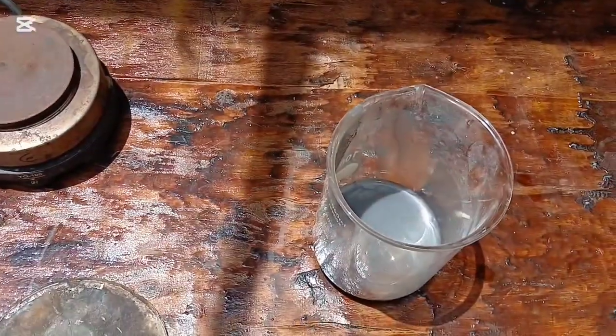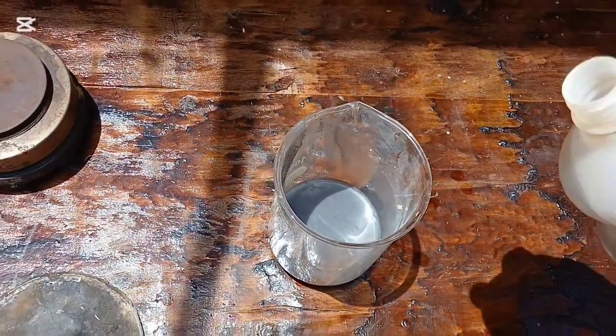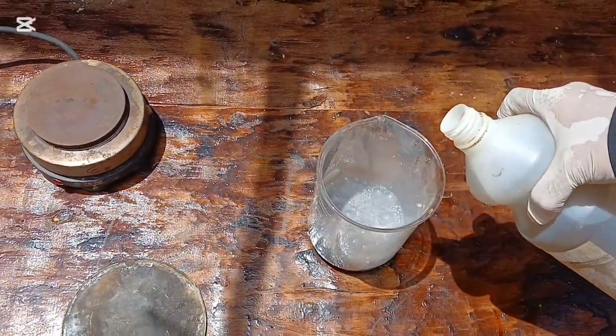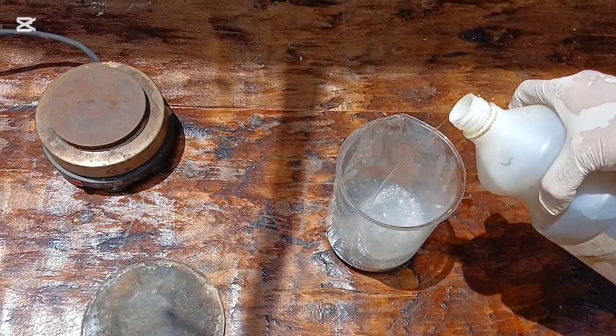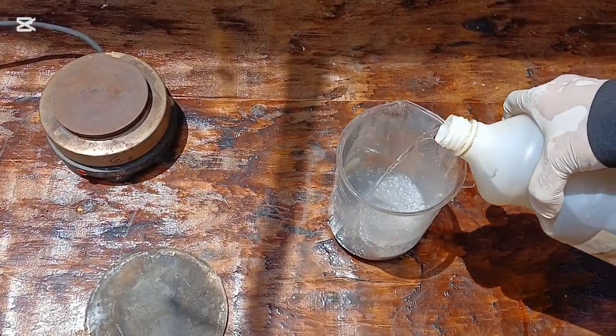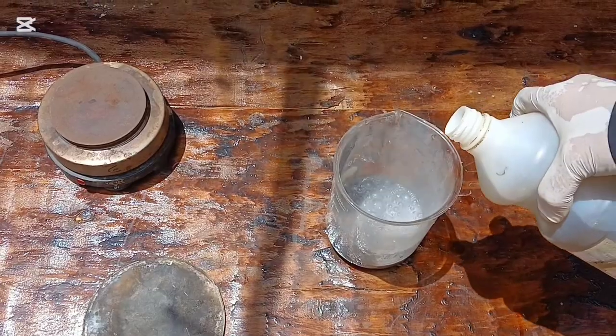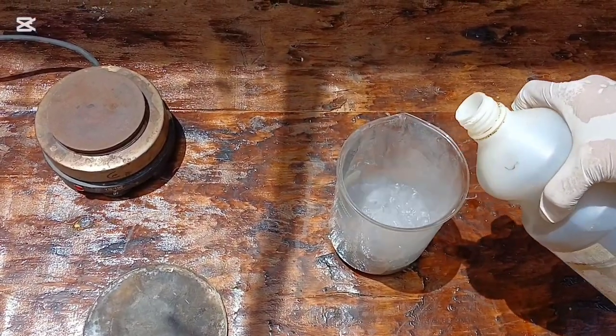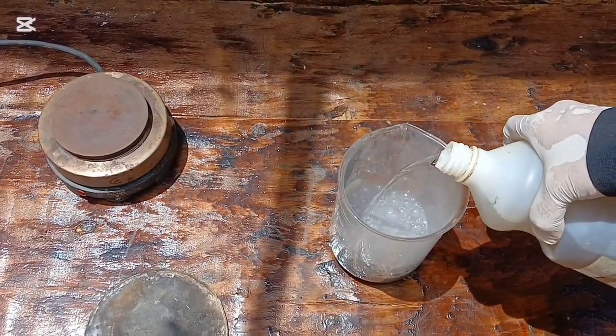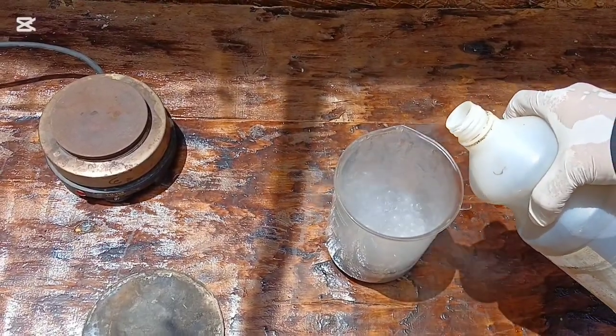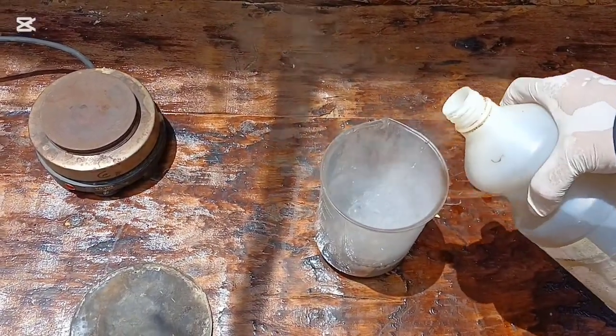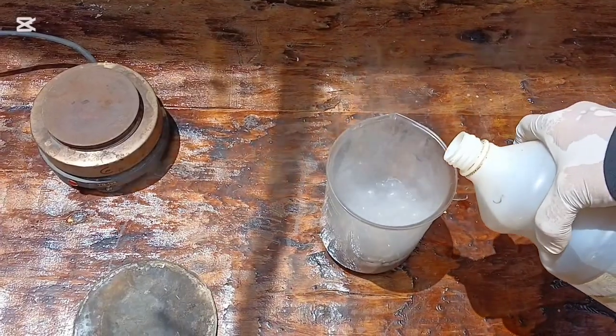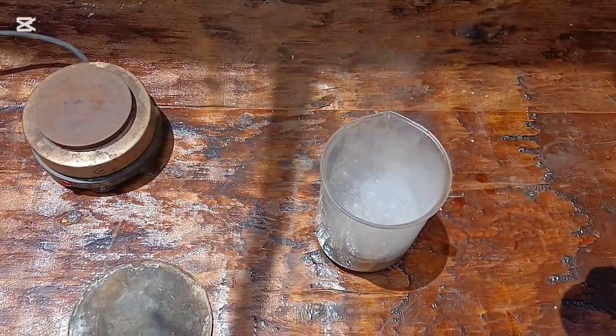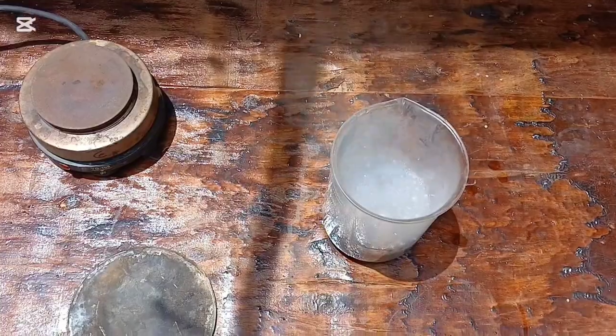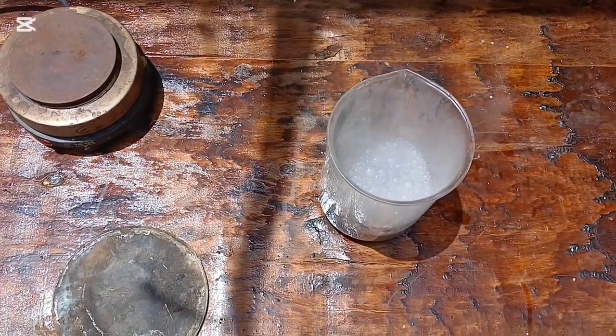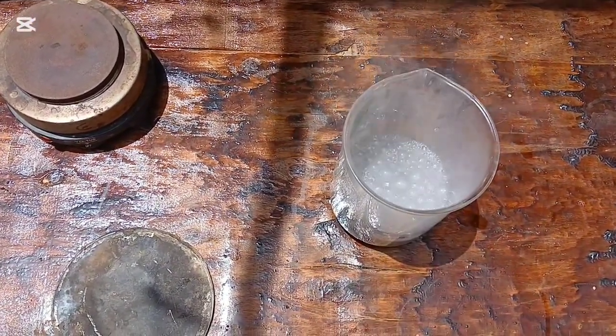It's important to stir the mixture gently and give it time, often several hours, to allow complete leaching. During this time, the solution will gradually change color, usually turning greenish or bluish depending on the concentration of nickel and cobalt in the mix. What's fascinating here is that this process is very selective. Gold and iridium, due to their chemical stability and resistance, do not dissolve in these simple acids. They remain at the bottom of the container, safe and separated from the other metals now dissolved in the liquid.